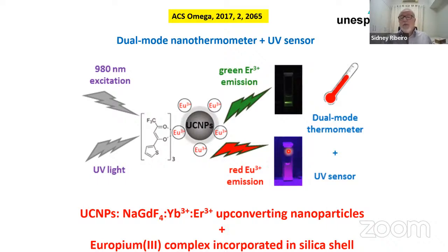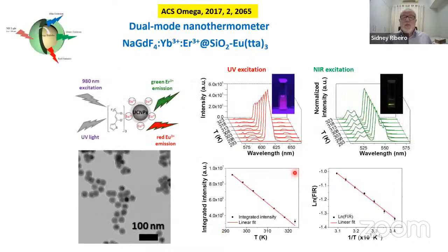So this is what we are calling a dual mode thermometer, because the upconversion emission depends on the temperature, as I showed before, and the red emission of europium also depends on the temperature. When you increase the temperature, the intensity will decrease. So this is what we call a dual mode thermometer. These are some measurements for these materials. You have here the europium emission. When we increase the temperature, the intensity decreases. And here you have the upconversion emission giving temperature information too.